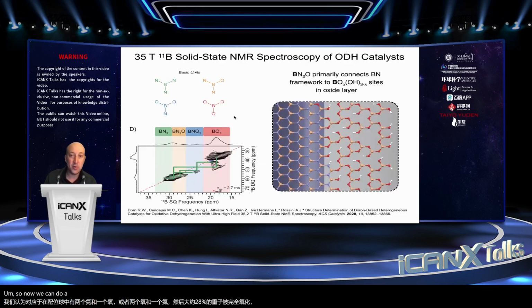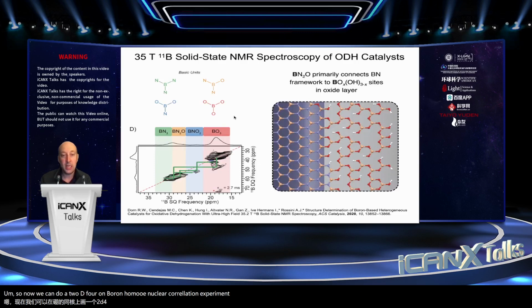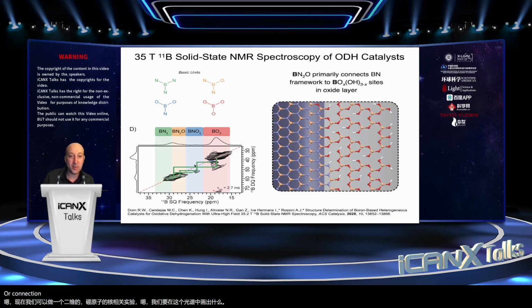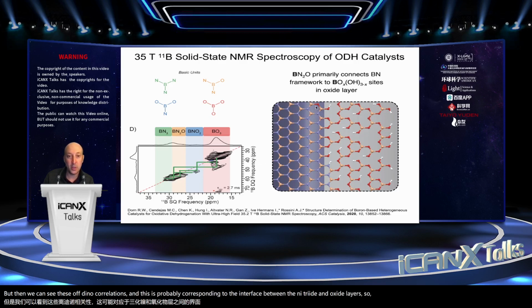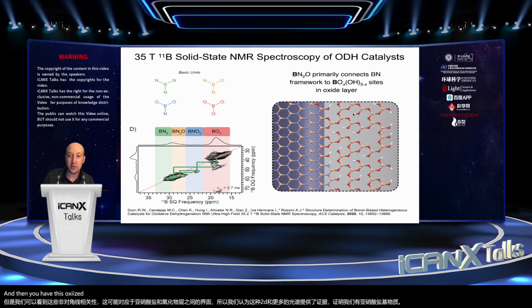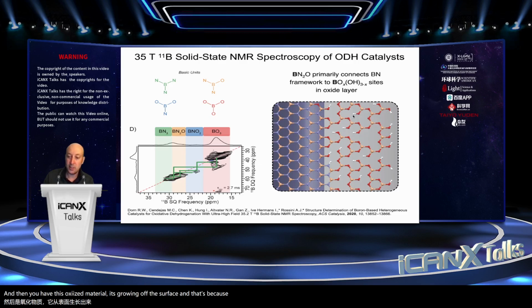So now we can do a 2D boron-boron homonuclear correlation experiment. So what we're going to map out in this spectrum are connections between boron NMR signals, as long as the boron atoms are within a couple angstroms of one another. So what's kind of interesting is we see these intense correlations within a group. So we have nitride coordinated to nitride, oxide show an intense correlation to oxides, but then we can see these off-diagonal correlations. And this is probably corresponding to the interface between the nitride and oxide layers. So we think this type of 2D NMR spectrum gives evidence that we have this nitride base of material, and then you have this oxidized material that's growing off the surface. And that's because you have these harsh reaction conditions where you have lots of oxygen and water is being formed as a byproduct as you dehydrogenate the propane.